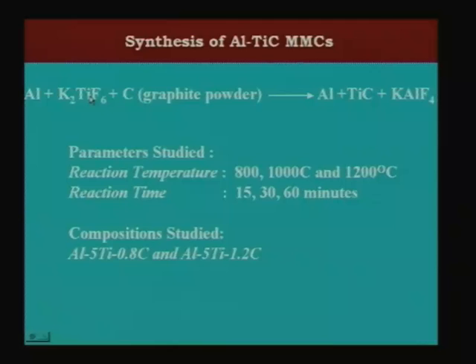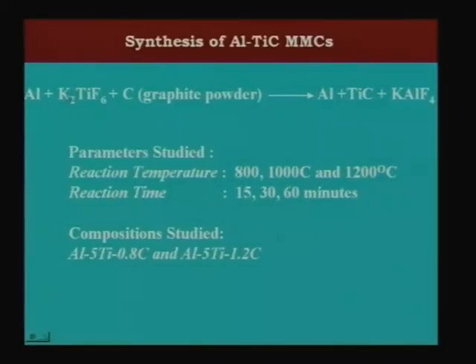So, that is why in TiC composite we expect the strengthening to be very good. Here, for titanium one can have all kinds of sources, one can add pure titanium directly to the aluminum, and you can take carbon as graphite powder, for example. But that process is going to be very costly, because titanium metal is very costly. So, instead the cheaper way to do it is adding a salt such as K2TiF6, as we have done before for TiB2, and add carbon as graphite powder, and this will give you a reaction: aluminum plus TiC plus KAlF4, which goes into the dross.